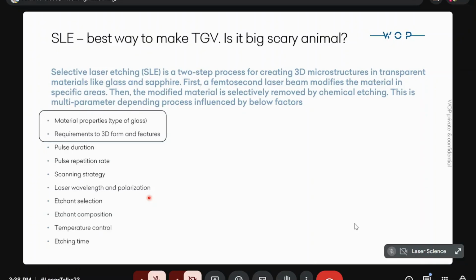So, selective laser etching, as I mentioned, is now the mainstream for making TGVs. And this is a two-step process: first creating 3D structures inside transparent materials by means of a femtosecond laser, and then the modified material is selectively removed by chemical etching. It is a multi-parameter process, which starts from the dependency on material properties, meaning if you have borosilicate glass or aluminosilicate glass, alkali, non-alkali glass, and it defines these parameters very much. So these are all dependent on which material you have and what you have to achieve.